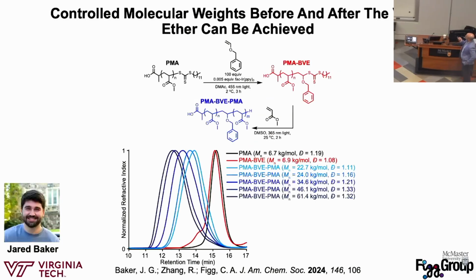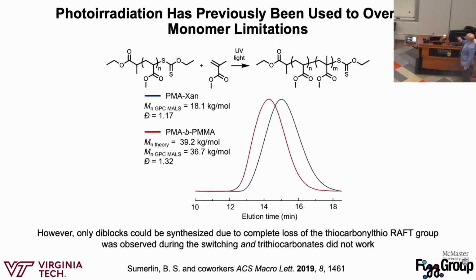So in the last slide, I was showing you a trithiocarbonate where this is a sulfur. You can take a xanthate. They have different absorption properties, different radical energies, but these xanthates more readily undergo homolytic cleavage. You can use UV light to, again, do this homolytic cleavage. And now the less activated monomer, or the less stable radical, is this methyl acrylate. And we're trying to chain extend this with this methyl methacrylate, which forms a more stable radical, which goes against conventional RAFT blocking efficiency, which I'll get into when I talk about the thermodynamics.